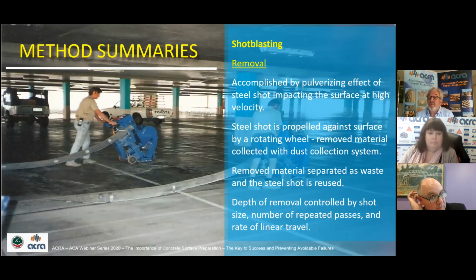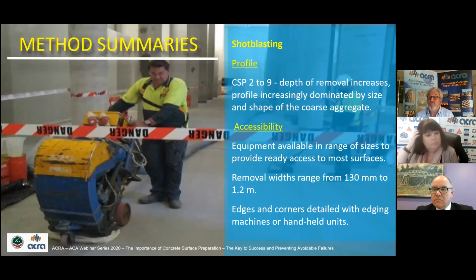Removal is by the pulverising effect of steel shot impacting the surface at high velocity. Steel shot is propelled against the surface. It's removed and collected with the aid of a dust collection system. The removed material is separated and reused. Profile can be anywhere from CSP2 to CSP9.